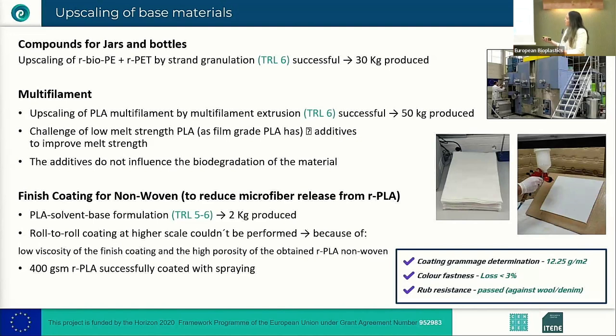also spoke about is what happens with the microfiber release. When we wash our clothes, in many of our clothes we have some microfiber release. Therefore, we wanted to guarantee that we have a final solution that is actually sustainable for the environment. And therefore, we worked with a finish coating for nonwovens where we were confident that we would reduce the microfiber release as well. This was a PLA solvent-based formulation, and we successfully produced between 2 and 5 kilograms at TRL around 5 and 6.